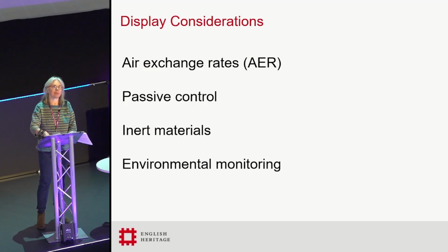A standard of showcase has been developed to enable low relative humidity atmospheres, that's less than 30% relative humidity. To do this, we carry out air exchange rate tests. We use predominantly passive control methods, i.e. silica gel. We specify inert materials, and we install standalone and telemetric environmental monitoring within each case.